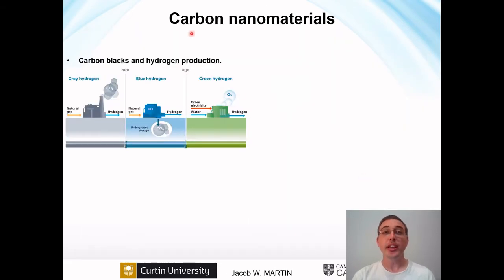But it also can be a useful material. So you can make quite useful materials out of soot. For example, carbon black, which is a heat-treated soot, which has been heavily carbonized, is being looked at the moment for the production of hydrogen. So you're probably familiar that hydrogen is produced from natural gas with water, and steam methane reforming produces hydrogen and a lot of CO2. So people have been thinking about storing that CO2, there's some difficulties there, or using electrolysis to produce hydrogen directly from water.